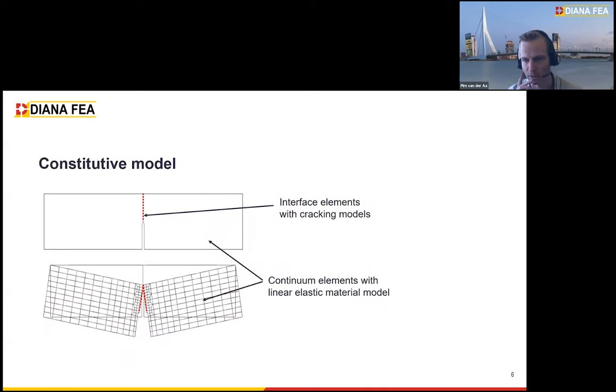Obviously, for a discrete cracking approach, where you only model the macro crack with, for example, an interface, and the continuum elements around it are just a linear elastic material, then you're not capturing the micro cracking. So if you model it like this, then you could consider using that small pre-peak branch. But in general, for nonlinear finite element analysis, we're using the smeared cracking approach. Then it is recommended not to use it.